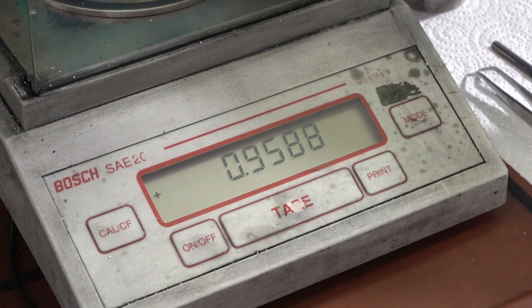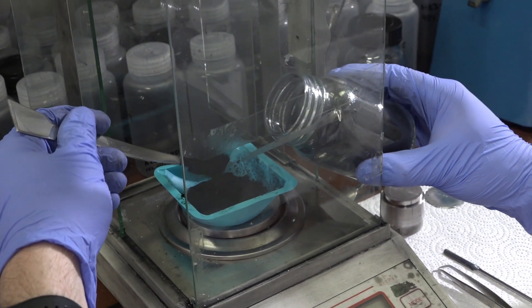What happens then is that we have a capillary effect where the electrolyte is dragged inside the electrode. The electrode can be produced in the lab by mixing carbon and teflon powders precisely together, pressing and baking them. After assembling the device, electrolysis can start.